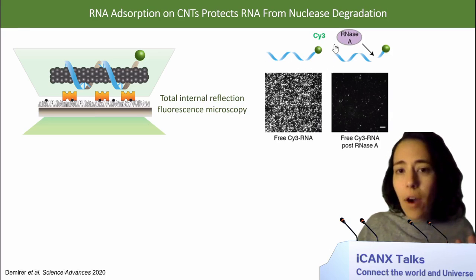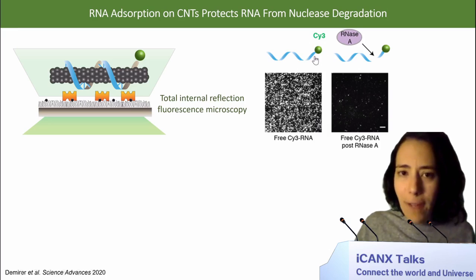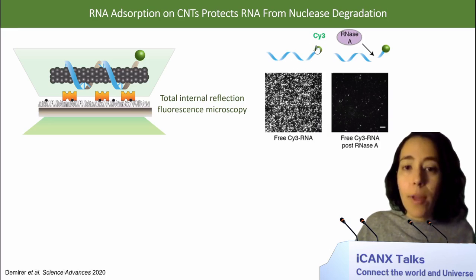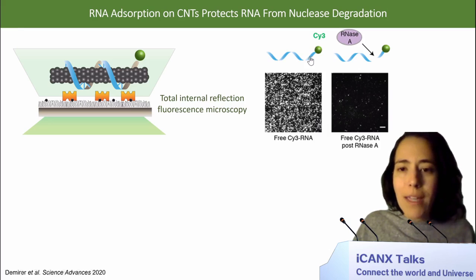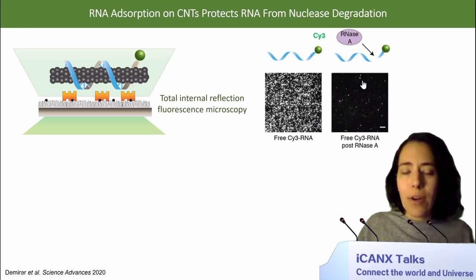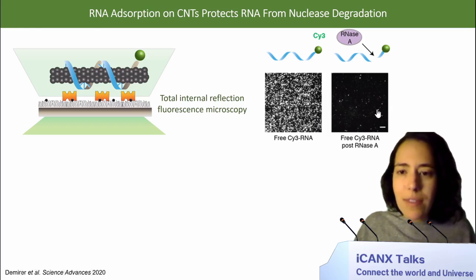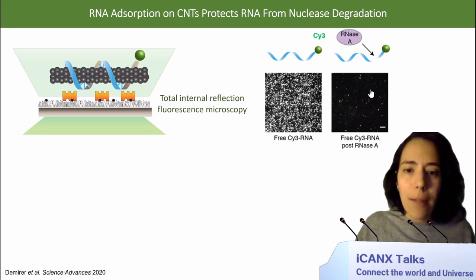So we can take the RNA strands in their single-stranded fashion that are, again, going to be targeting GFP knockdown and label them with a Cy3 dye. We can then take these individual strands of Cy3 labeled RNA and put them on the surface of a microscope slide. What we can then do is treat this slide with RNase A for 5 minutes and then quantify the amount of fluorescent spots that are decreased post-RNase treatment that suggest degradation of those spots. And as you can see here, following RNase treatment, we see almost complete degradation of the RNA.